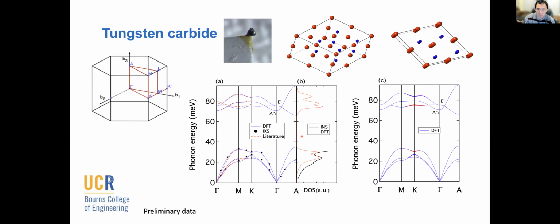So this is our dispersion measurement using inelastic X-ray scattering, in comparison with the density functional theory calculation. As you can see, the agreement is pretty nice, and it agrees well with the literature calculation, and it also agrees reasonably with our neutron scattering experiment for the density of states. But what's more interesting is shown on the right-hand side. If we calculate the phonon eigenvectors and use them to calculate the angular momentum carried by the phonon modes, this is what we see.